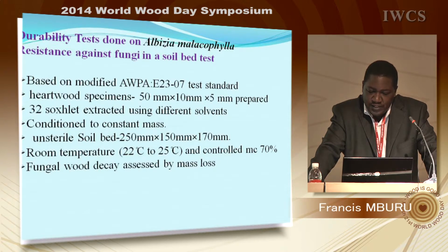Then I used an unsterilized soil bed in a container of those dimensions, 250 by 150 by 170. Then I incubated at temperatures ranging between 22 to 25, and then controlled the moisture levels to about 70%. The fungal decay was assessed by mass loss.